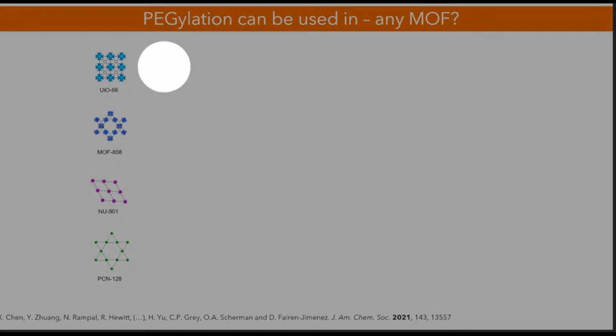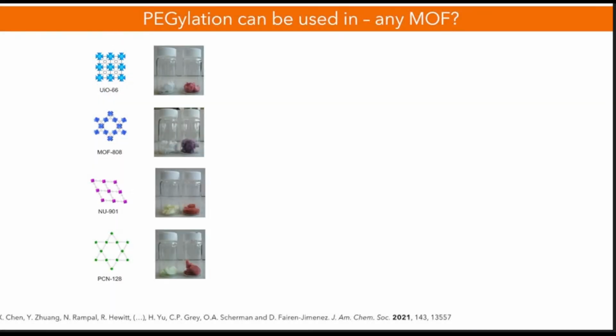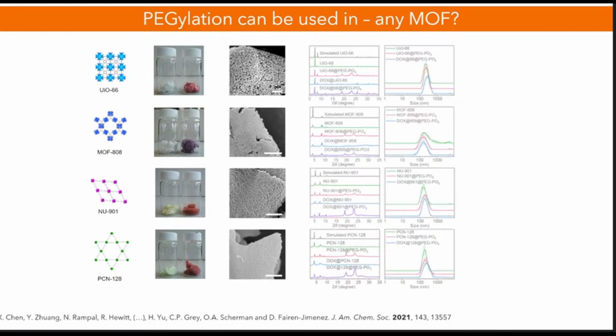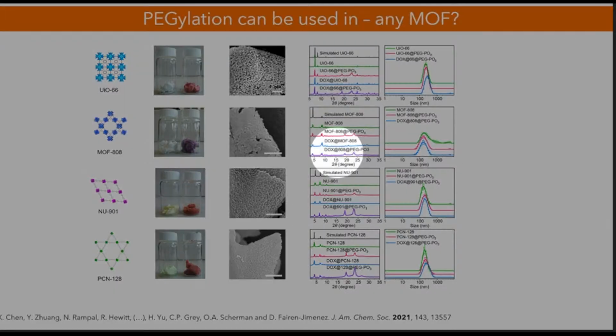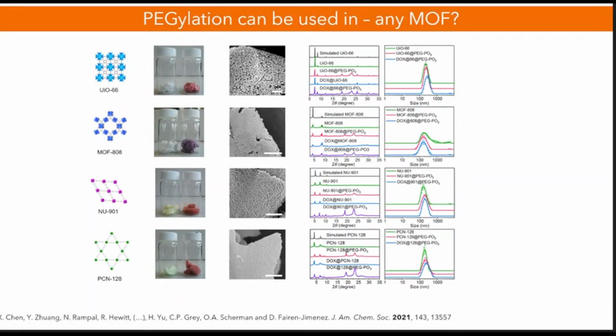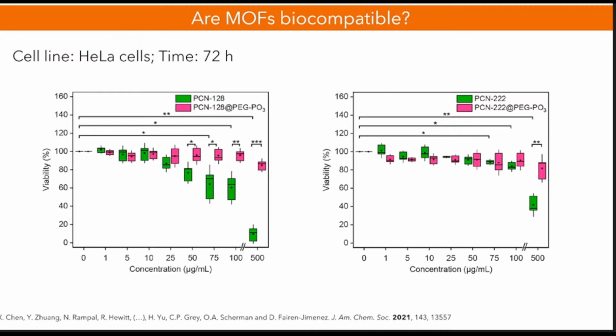Can we use this for any MOF? The answer is yes. We have been trying this with different materials, not only with zirconium, but also with different metal clusters. And these are the dry materials, beautiful. And then we can always compare this with experimental X-ray diffraction, but also with DLS to see what are the effects on the particle size. And we can see that there are no changes, which means the materials are colloidally stable. Very happy with this. That was published in JACS this summer.